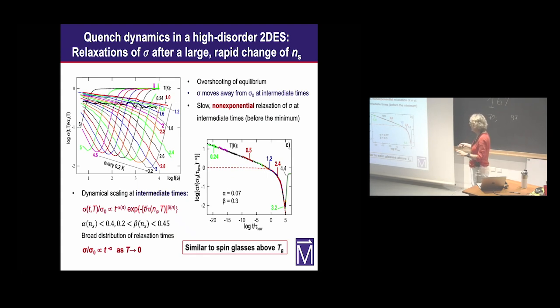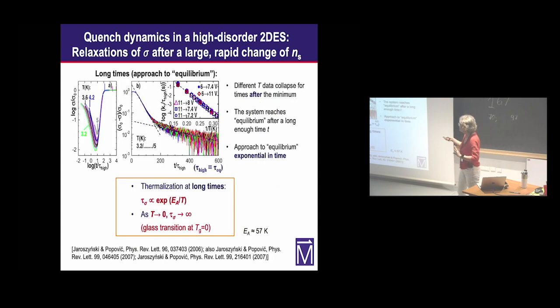Above the glass transition temperature, I need to get to the most important things. If you look at the approach to equilibrium, this is a simple exponential process. You can extract the characteristic thermalization time, like everybody has been doing, and you already saw that it depends very strongly on temperature. In fact, it diverges in the zero temperature limit, which again tells us that there is a glass transition at zero temperature.